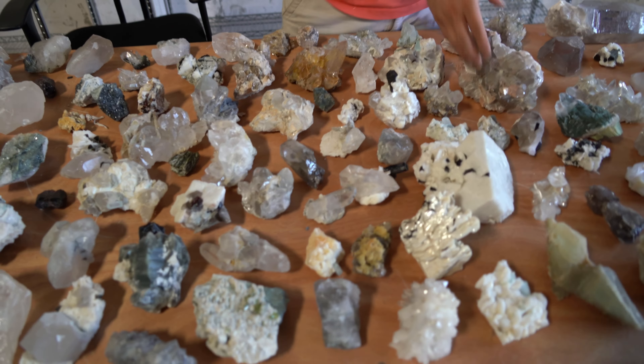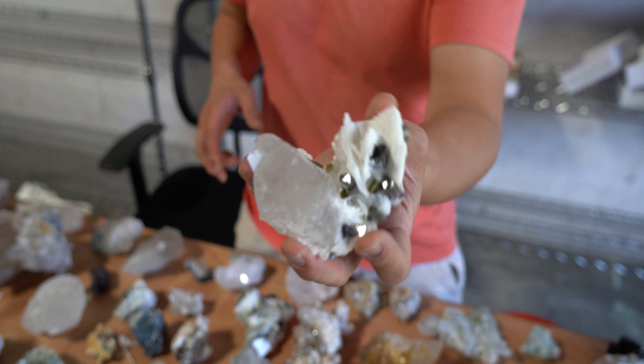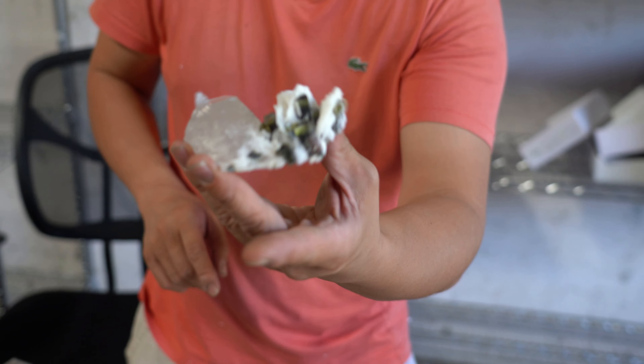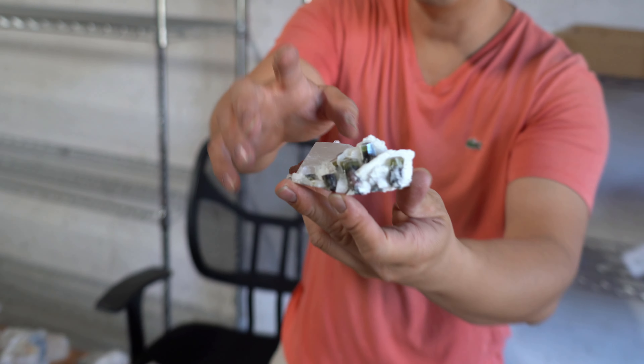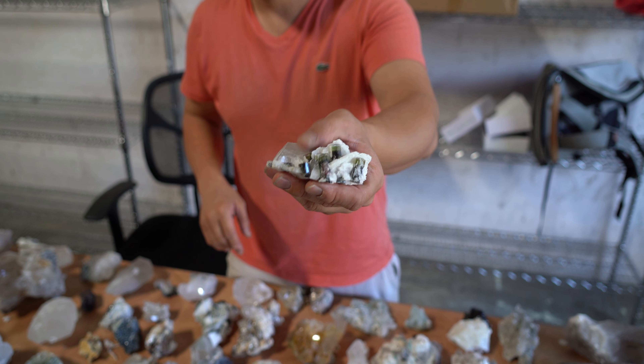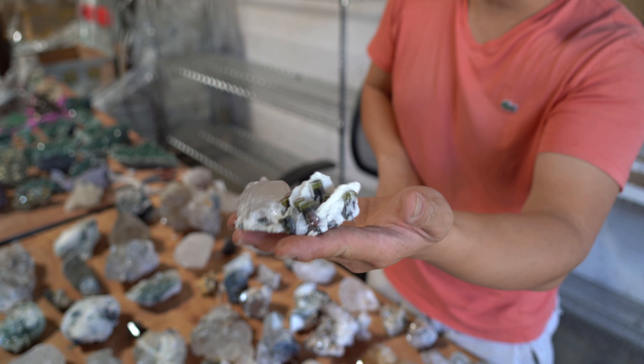A lot of minerals — if you see the quartz is extra smoky and very dark, it's heat treated. Now, those two were the best. What other ones impressed you? I like this nice little tourmaline from Astak Nala valley, which is near Skardu district. Look at that — tourmaline with clear quartz and clevelandite crystals. The clevelandite is the tabular flake-looking ones. This type of tourmaline — a lot of people in the marketplace in Pakistan heat it. The cap turns pink, but they don't disclose that it's heated. So this is the natural state. On heated pieces you'll see the cap turn purple and the quartz turn gray or black. Clevelandite won't change.